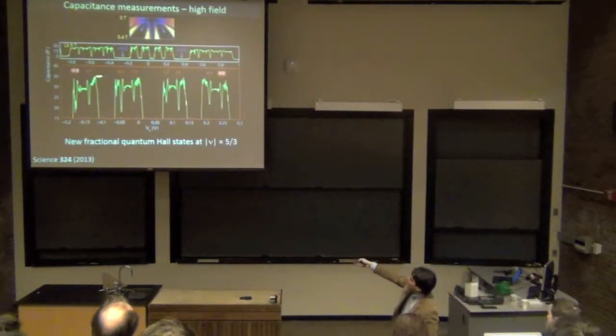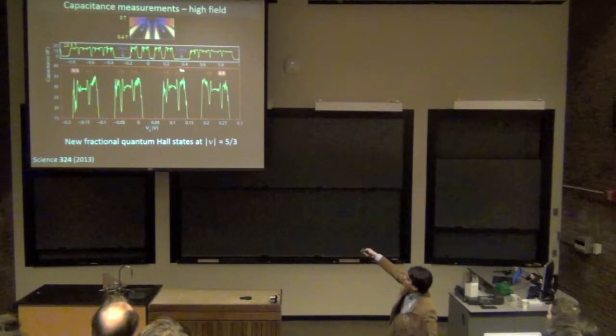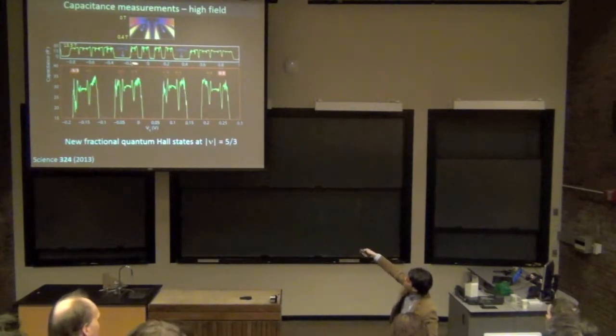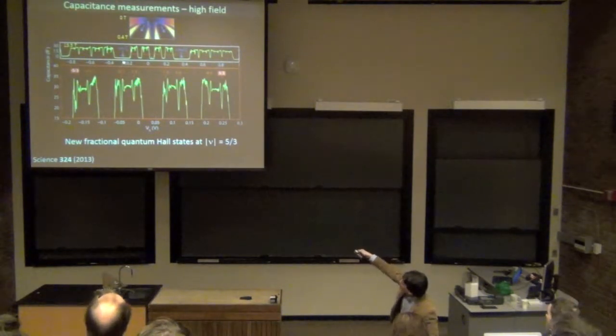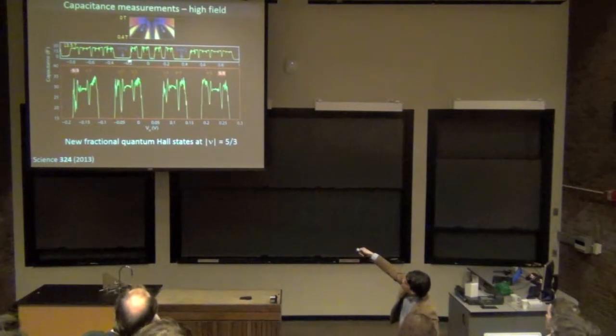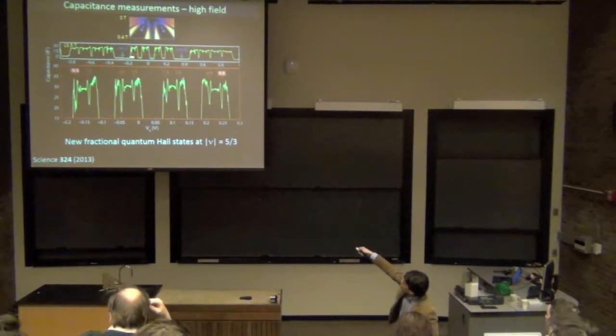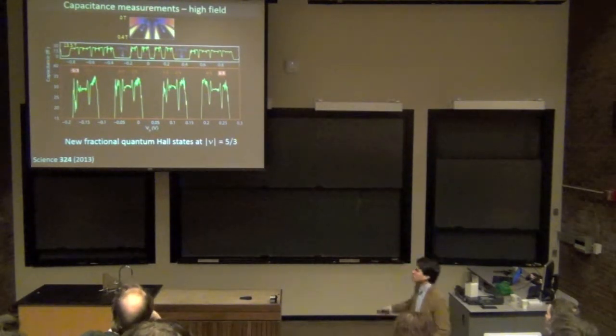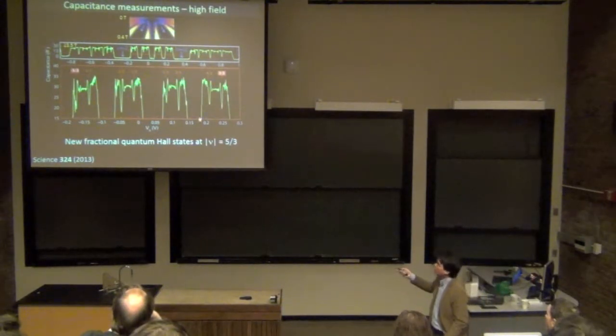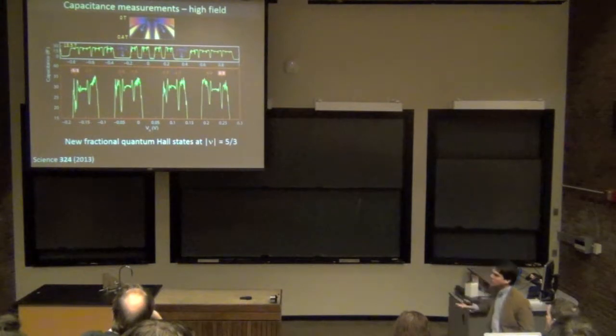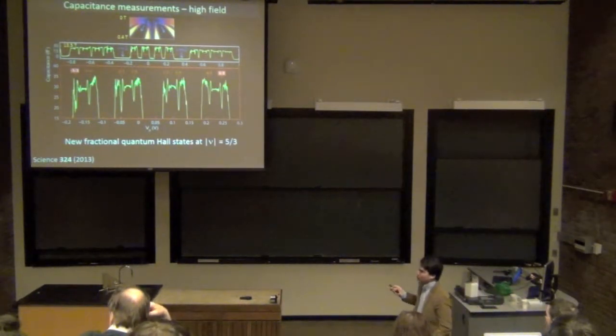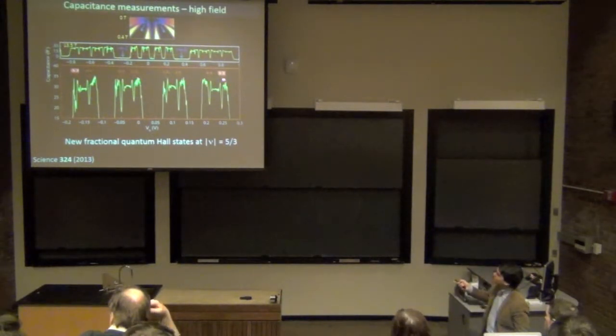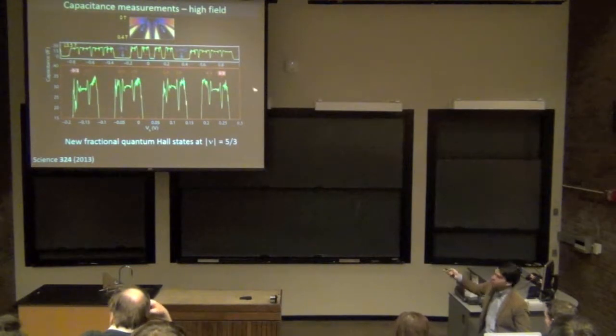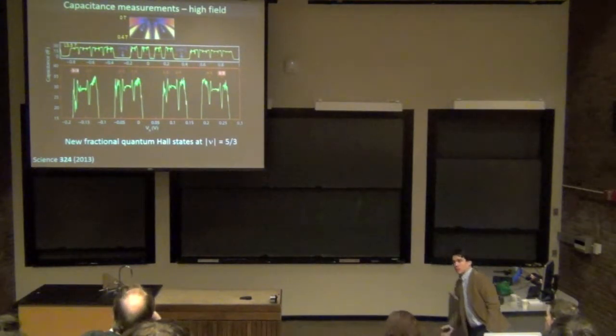If we look at a trace with respect to electron density here, you can see there's gaps at low field. Actually, not a low field trace on there, but as we increase the magnetic field, you can see this Landau fan spanning out. You can see these nu equals plus and minus two gaps here. These are cyclotron gaps, broken symmetry gaps. This is the lowest Landau level with the four states in there. If we zoom in on the lowest Landau level, we can see fractional quantum Hall gaps. This is nice because we can't see these as clearly in transport. Capacitance turns out to be a very nice way of looking at very sensitive gaps. But these particular gaps, the plus and minus 5/3, had never been observed before in graphene.